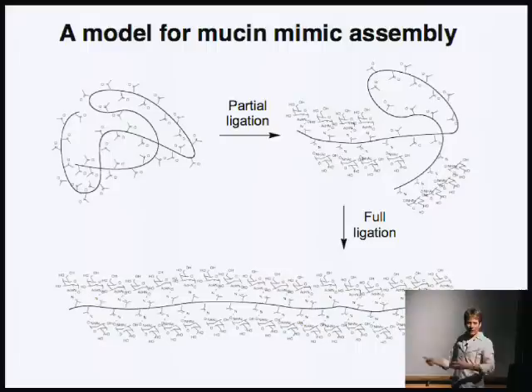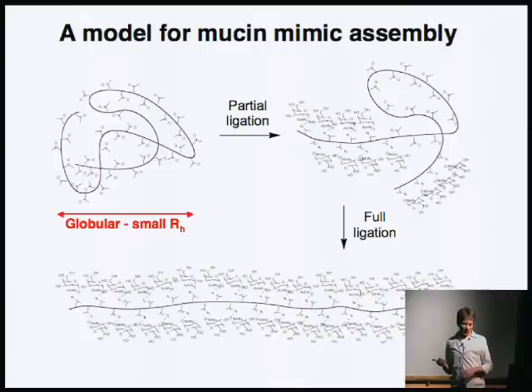If the polymer gets much longer, which is the model that we're following, then we have some confidence that the backbone has been rigidified. So how do we determine if the polymer does go from sort of more globular to more rigidified? Well, we can measure a parameter that's called the hydrodynamic radius, which is basically the volume that these polymers occupy. And that value can be obtained using a gel permeation chromatography instrument, or GPC, kind of a standard instrument used by polymer chemists.